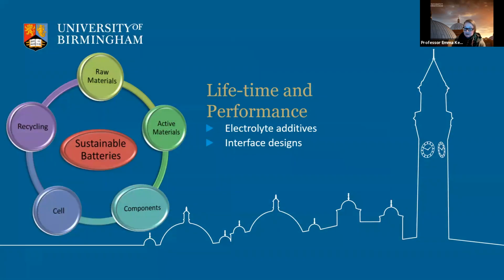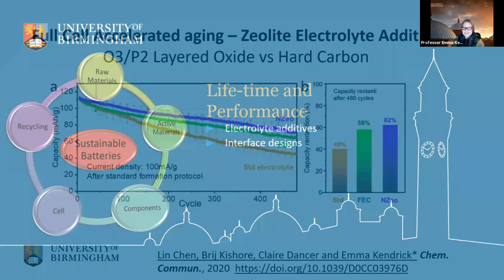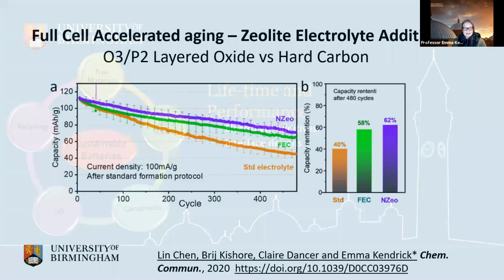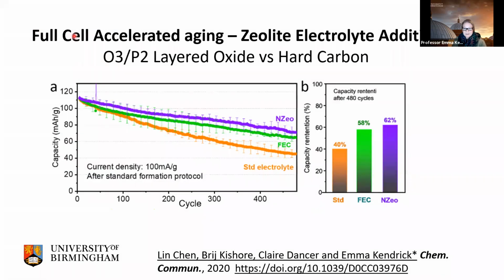And we did some work on some full cells looking at electrolyte additives. And this shows you here a full cell. And this is in collaboration with a project with Faradion, who provided us with the cathode materials. And you can see here, just by adding a nanozeolite additive, we actually prolonged the lifetime of a full cell quite significantly compared to something which had no additive in at all.